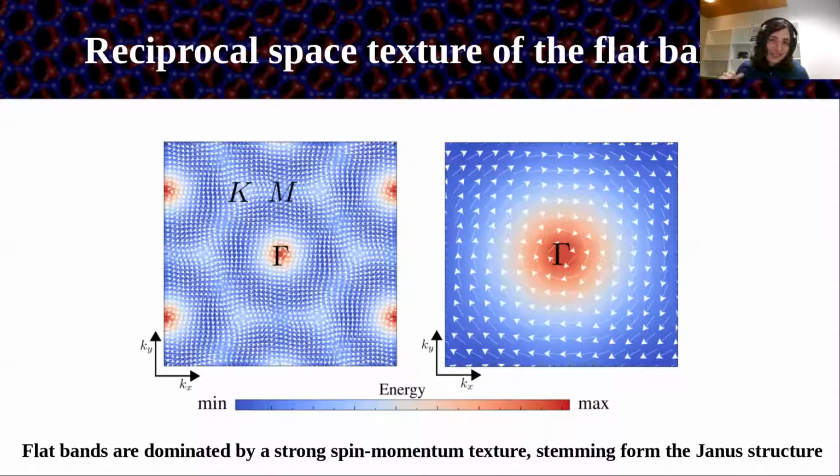So you essentially see that all the low energy sector is completely dominated by the Rashba spin orbit coupling that is of course inherited from the individual Janus monolayers that we have. So essentially here what we have is a flat band system with the flat bands showing an extremely strong spin texture. And the question that we can ask ourselves is, well, what is the consequence of this when we think about potential correlated states here? And that is, of course, something that we can systematically tackle.